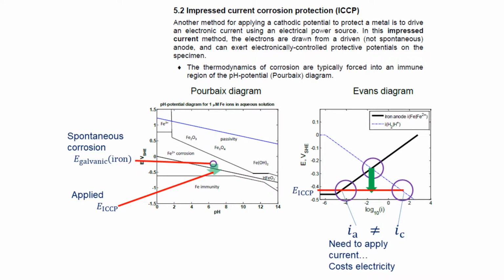In the Evans diagram for kinetics, we can find out what that corrosion rate is. We're just looking for the intersection of the lines for the anodic and the cathodic reactions as before, and the spontaneous corrosion current density is going to tell us that log base 10 of this corrosion current density is about -2 in whatever units we're thinking about, maybe amps per square meter, and maybe this is unacceptably fast.